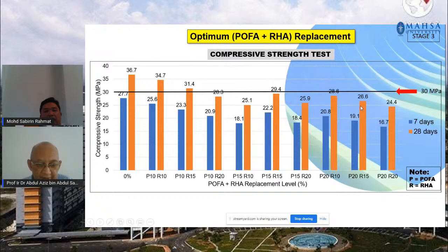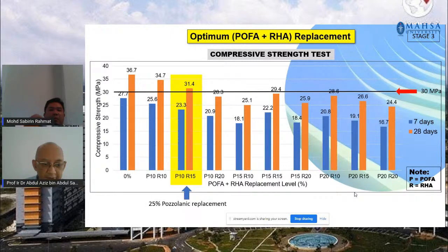And what we can observe with this combination of POFA and RHA is that with 10% of palm oil fuel ash and 15% of rice-husk ash, we have managed to obtain a value higher than 30 megapascal. As you can see, from 10% POFA and 10% rice-husk ash, we also managed to get 34.7, but we selected this one because we have a higher amount of waste material in this concrete mix, which is 10% and 15%. So that's about 25% of waste material in this concrete mix, and yet we still managed to get higher than the target concrete strength of 30 megapascal. All right, so 25% of pozzolanic replacement was achieved for this particular study.